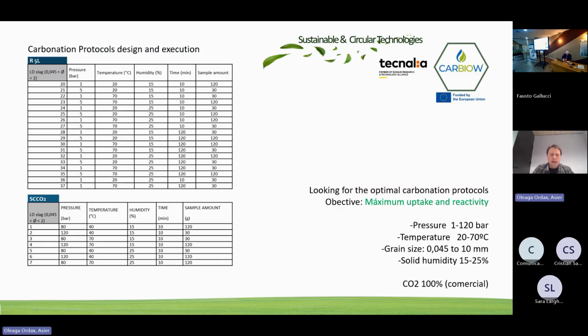After knowing very well the material to be carbonated, the LD slag, we designed protocols, changing variables of pressure, temperature, humidity. The goal is to produce the maximum uptake, and also the reactivity of the material, which is characteristic for doing cement. So we work with low and high pressures, moderate temperatures, different grain size, very fine to coarse, and always solid humidity between 15 to 25, and CO2 100% pure commercial,